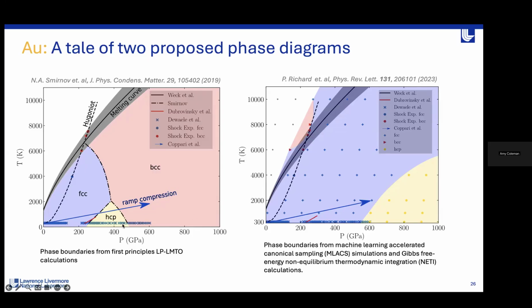The other thing present on these plots: we have a series of crosses down here. These represent room temperature diamond anvil cell experiments, which are showing that actually the FCC structure of gold is present up until quite high pressures, at least 600 GPa, and depending on what you believe from results, maybe even a terapascal.